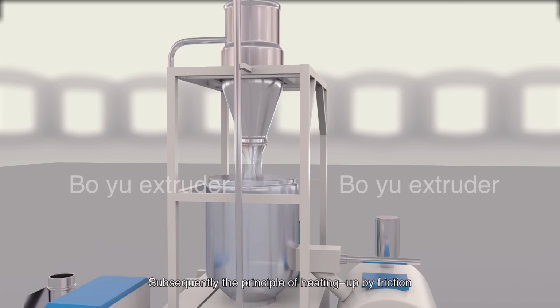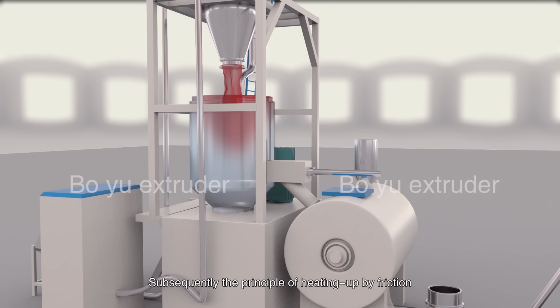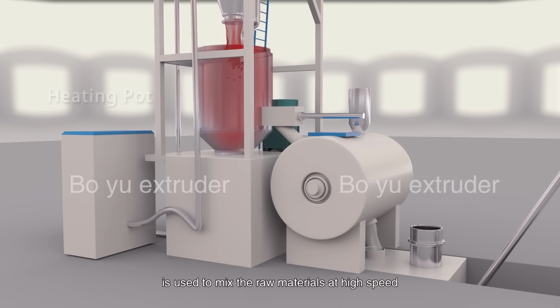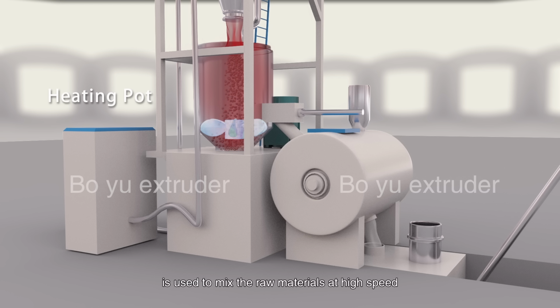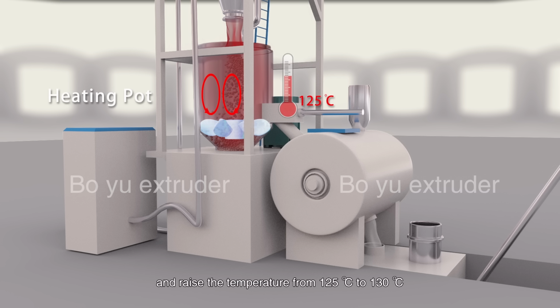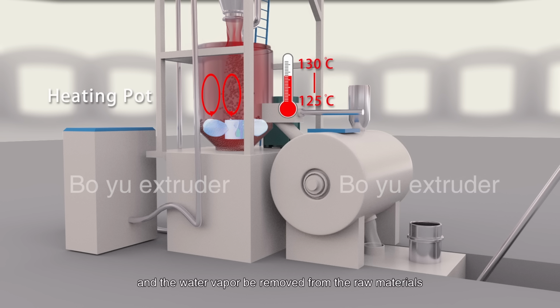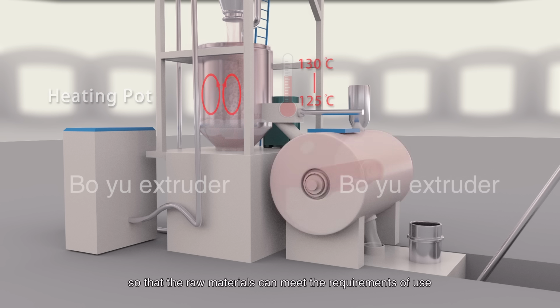Subsequently, the principle of heating up by friction is used to mix the raw materials at high speed and raise the temperature from 125 degrees centigrade to 130 degrees centigrade, which will make the processing aids melt and the water vapor be removed from the raw materials, so that the raw materials can meet the requirements of use.